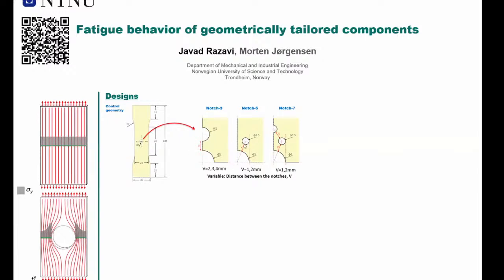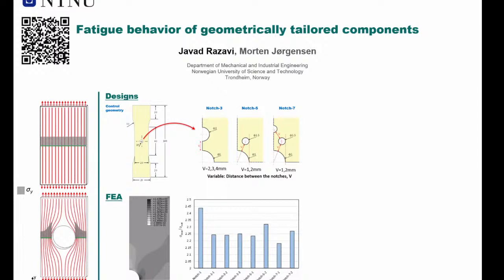Okay, so these are the three cases that we had, and we wanted to see how the added notches are going to change the maximum stress ahead of the notch. We performed some finite element analysis on, again, 1/4 of the geometry because of the double symmetry that we had. And the results showed that, comparing the results of the specimens with more than one notch in them, they all had a reduction of the maximum stress ahead of the notch. The reduction is not that high, it's around 10%, but they all experienced the same thing.